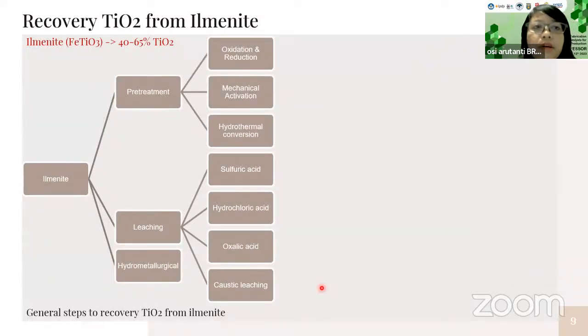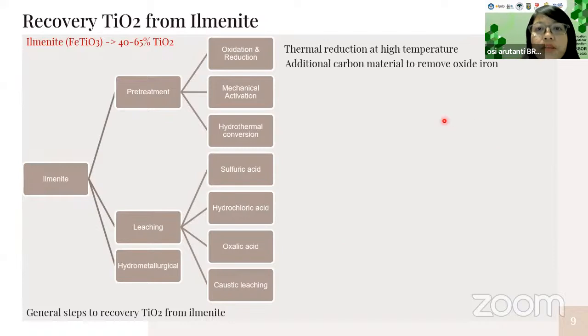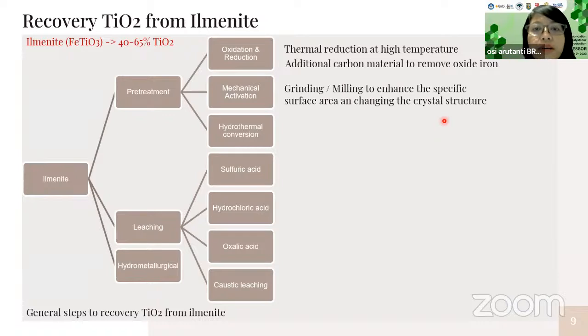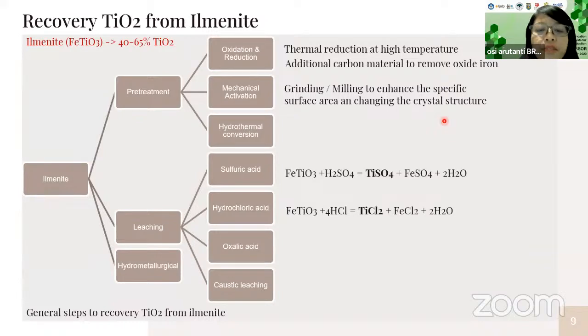This is the way to recover titanium dioxide from ilmenite. There are three steps. The first is pretreatment, and then the second one is leaching, and then hydrometallurgical. For pretreatment, there is an oxidation and reduction process, usually by thermal reduction at high temperature or addition of carbon material to remove iron oxide. And then the second one is mechanical activation. It can be done by grinding and milling to enhance the specific surface area and change the crystal structure. And then the hydrothermal conversion.